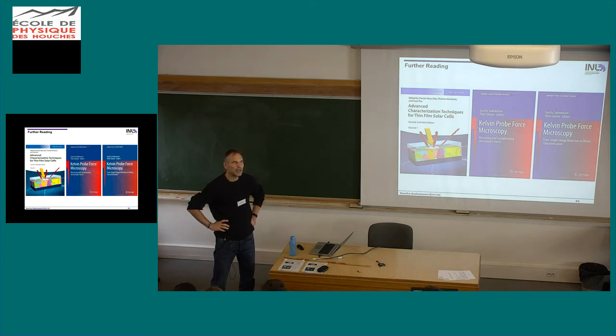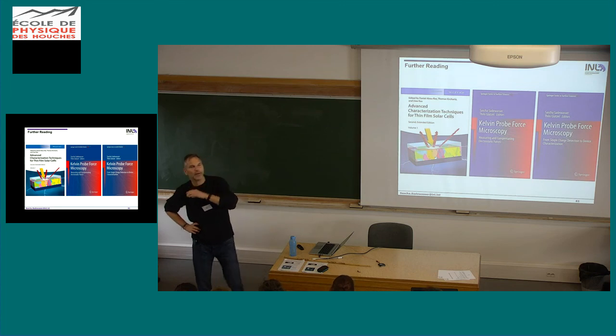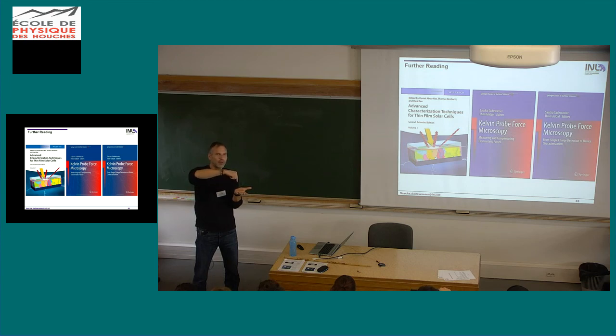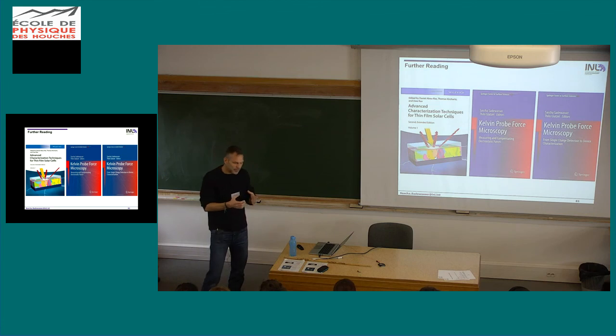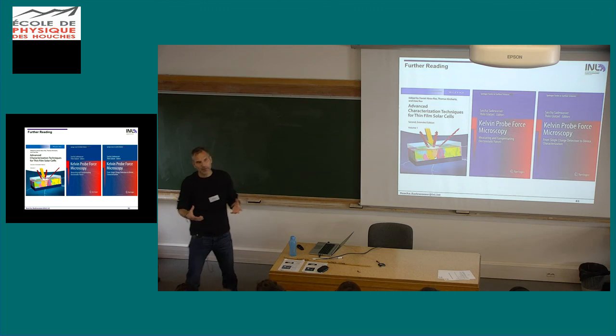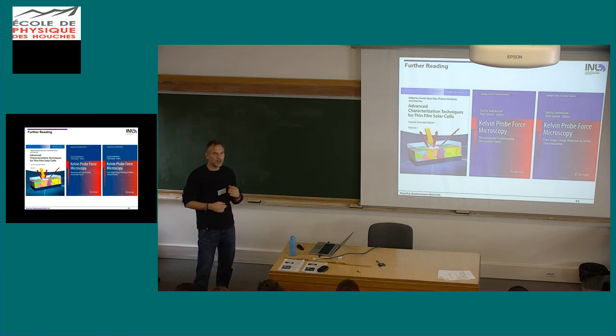They illuminate the sample, and they did this, I think, on a cadmium telluride, if I remember correctly, so they can illuminate from the backside. So one of the problems, of course, if you have your tip and you want to illuminate from the front side, you normally use a laser, and it's never sure how much intensity actually gets to the point where you're measuring. And then, as you explained yesterday, there's charge carrier diffusion if you don't illuminate the whole sample. So it's a very tricky situation. Then, of course, the sharp tip also causes reflections and so on. So it's not easy to know what your light intensity is.